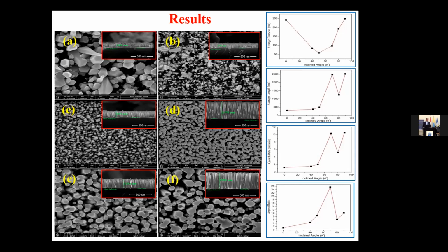Also, we can conclude from the figure that the optimum substrate inclined angle is 70. You can see from the figure we have uniform size, shape, alignment, and high aspect ratio and high growth rate. Also, most of the zinc oxide nanorods have the same shape and the same size, and a completely hexagonal shape.